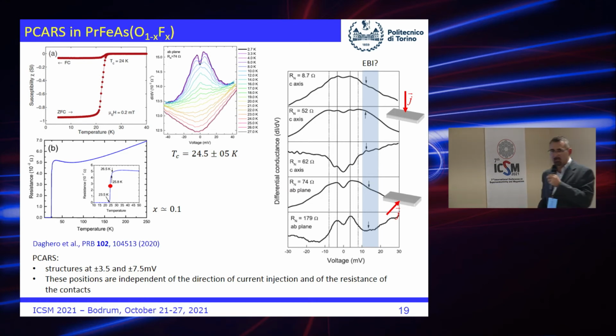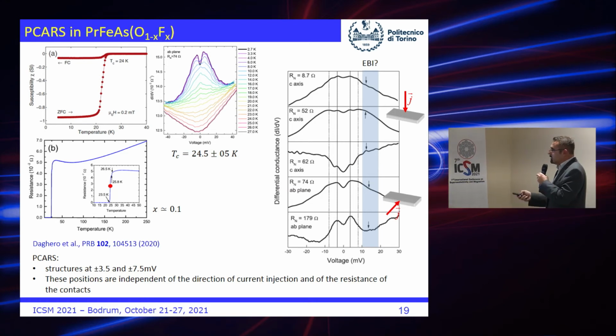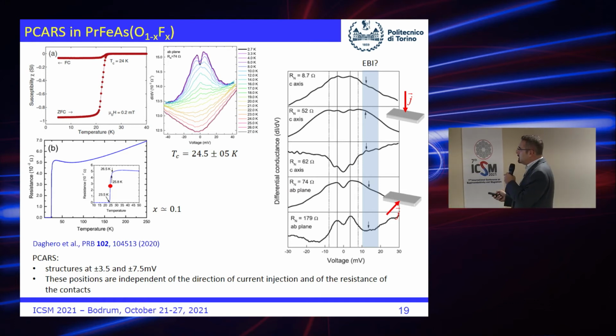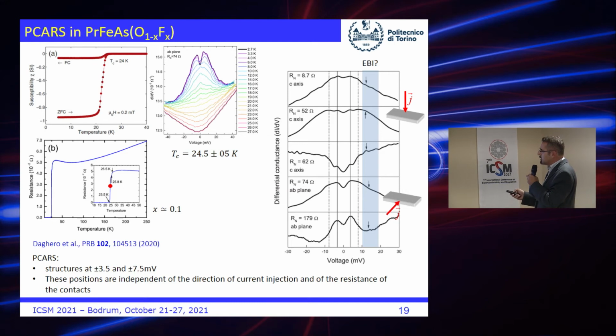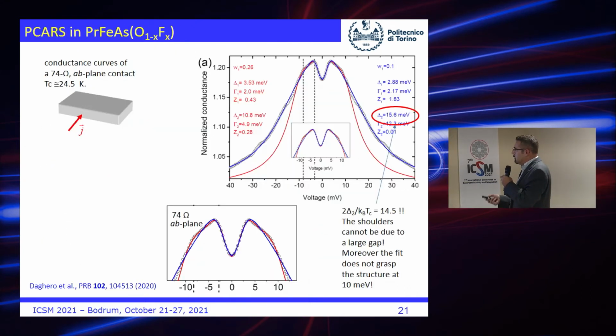with the magnetization transition. These are some spectra with very different resistance, from 180 to more or less 9 ohm. And you see that despite this very large range of resistances, there are structures that always fall in the same points. You see, these are likely to be related to the small gap. These are likely to be related to the large gap, and there are still other structures.